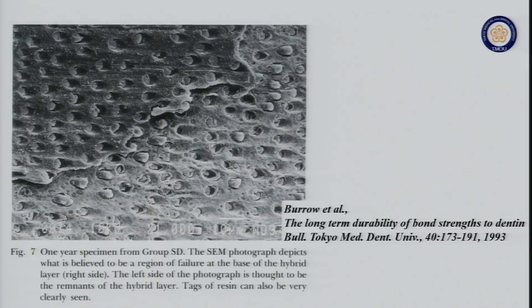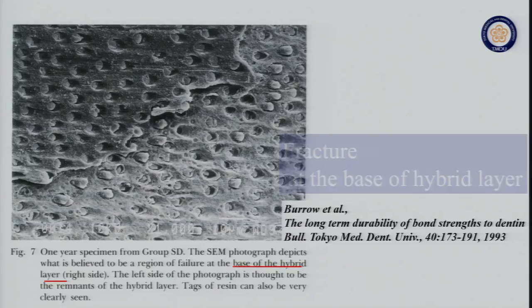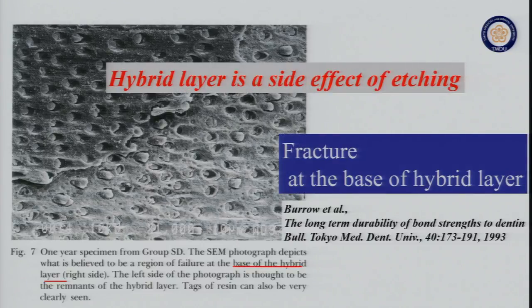So when we test the bond strength after the storage of the specimen in the water, many of the specimens in the case of the etch and rinse technique showed the fracture at the bottom of the hybrid layer. So that means that the hybrid layer may be a kind of weak point at the interface.